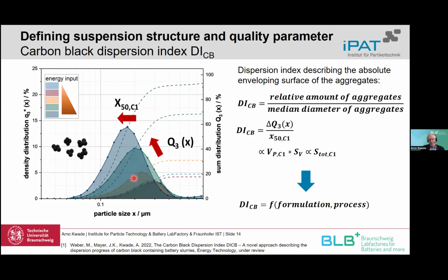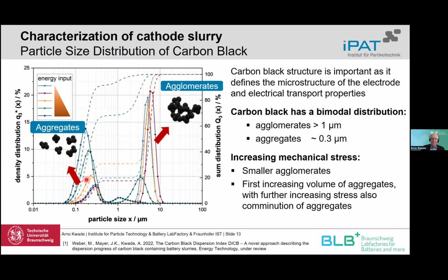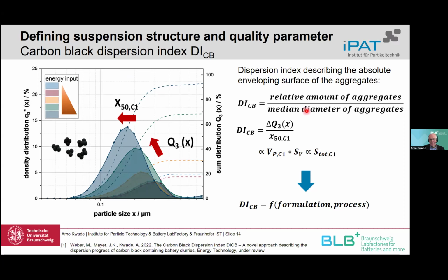And we're looking for one parameter which can be used as a measure or a characteristic of this performance. And we found that the enveloping surface of the aggregates is a good measure for that. And we can find a characteristic value for that if we calculate the relative amount of aggregates. That means what is this area under the left curve here on the left side compared to the entire curve, and what is the median diameter of the aggregate. So we multiply the amount by the specific surface of these aggregates, and by that we get a measure we call the dispersion index.